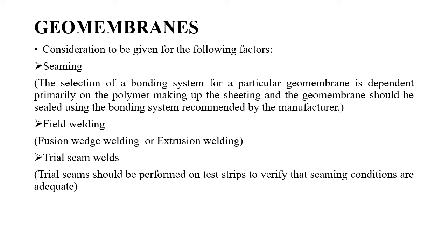On hot days, where the air temperature is expected to vary appreciably through the day, welding should be confined to early morning or late afternoon. This will prevent excessive wrinkling or spanning. That is, the strain induced will be less when you do it during such weather conditions.